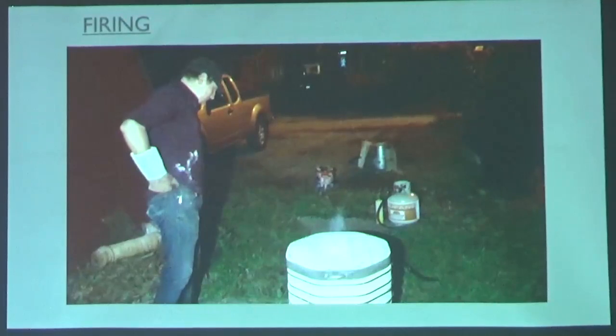Now, some people will. I've seen potters do this where they will actually put glaze, like what you'd use on a functional piece of ceramics, onto a piece of what they call greenware, which is clay that has not been fired at all yet, and they will fire it all the way through its process without bisque firing it the first time. And those people are daring. It's possible if you have a really good understanding of the ceramic chemistry and what it takes to do that.